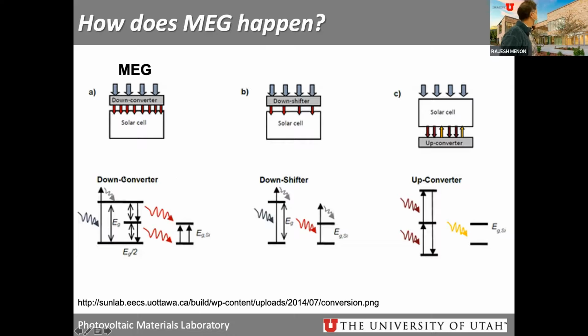How does that work from an energy band diagram, very simplified band diagram? You have the blue photon with lots of energy coming in here. The electron gets excited from the valence band all the way into the conduction band, but way into the conduction band, not close to the band edge. It relaxes very quickly. That's a very, very quick thermodynamic process. Now, instead of relaxing directly and fluorescing or emitting light, it goes through 2 steps. It relaxes to an intermediate level. So the material is engineered to have this intermediate level, emitting a red photon, and then it relaxes again, emitting another red photon. So you end up having 2 photons here. And that matches the band gap of the silicon in this example, Eg of silicon.